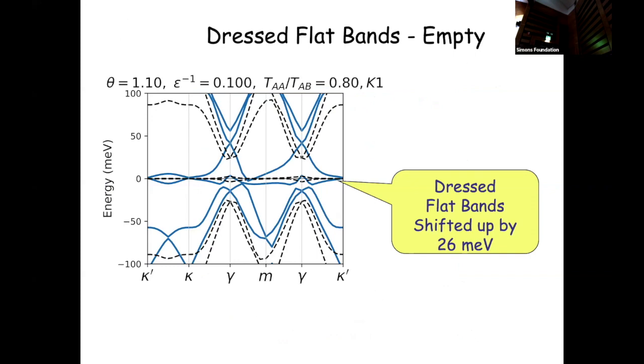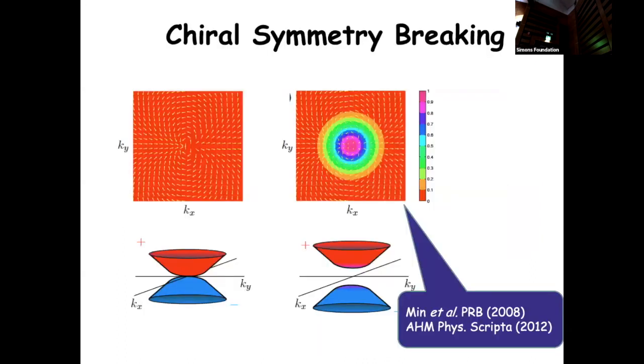the shape of the bands, even when you don't include quantum fluctuations within the flat band, the shape of the flat band depends a lot on the strength of interactions, because of exchange interactions with the negative energy sea. And that's an unusual feature connected to my next point, which is that the wave functions in these graphene multilayer systems, even without the Moiré modulation, are very sensitive to wave vector. This is a plot of the bilayer state as a function of momentum in some Bloch sphere representation at the quadratic band touching point of bilayer graphene.